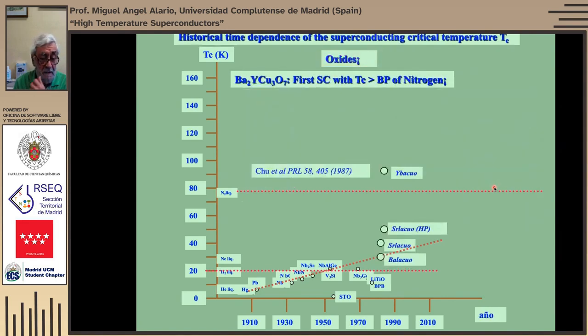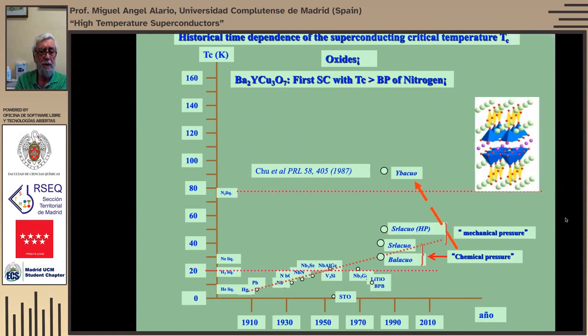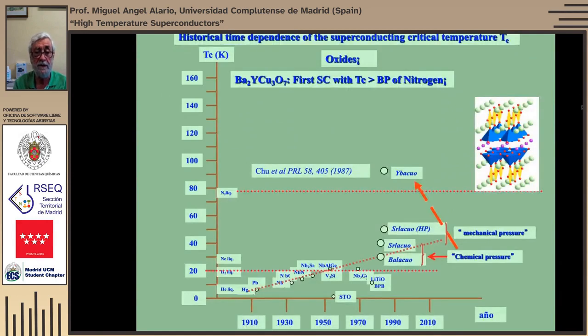And then, immediately, chemists in particular started to make substitutions. The first substitution was barium by strontium, something we call chemical pressure. But then other people applied actual mechanical pressure. And both things increased superconductivity. A little later, YBCO appeared. YBCO is very similar to La-Ba-Cu-O, and is based on the perovskite structure. You see here a perovskite, but with some oxygens missing. This is why it is O7 and not O9, as it should be. But anyway, perovskite-based materials were the clue for the cuprates.